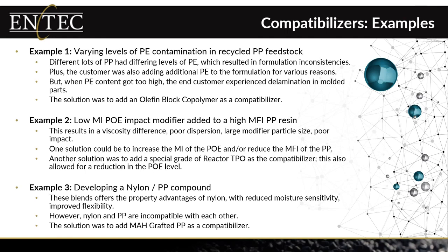However, we can also look in a case like this at using an acrylic acid or an ionomer as the compatibilizer. And because they don't have a chemical reaction, they don't as negatively affect the melt flow index while still offering good compatibility between those two polymers. Once again, here's a case where we can utilize something a little bit different, not quite as common as the MAH grafted materials, but we can overcome some of the limitations.